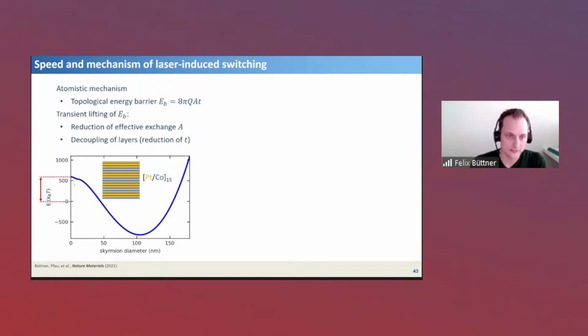And then our layer system here, you also asked about the material. The system here is a multilayer of cobalt platinum, or in other cases platinum, cobalt iron boron. This is a succession of layers of magnetic and non-magnetic materials. What the laser is doing is also decoupling all these layers, meaning that the dynamics in one of those is separated from the dynamics of the next one.